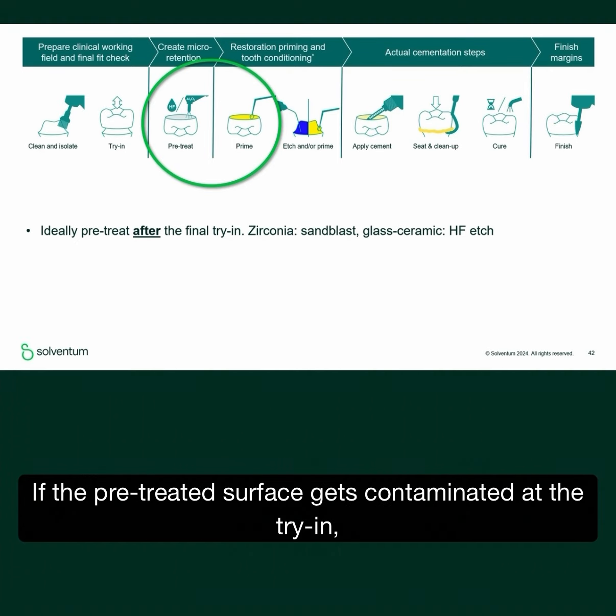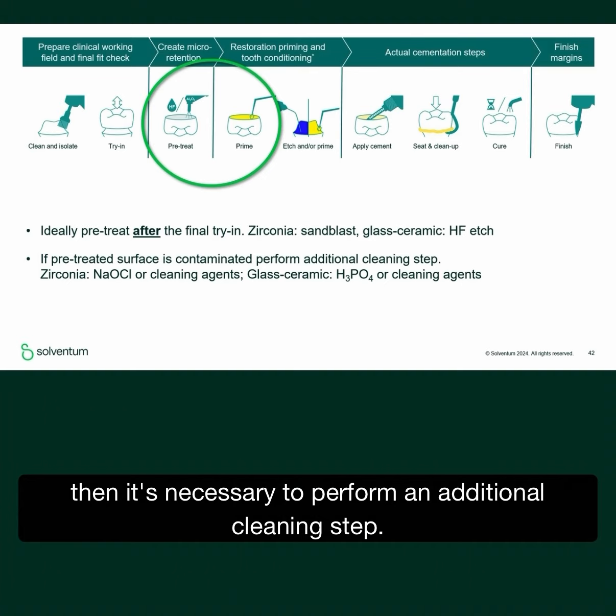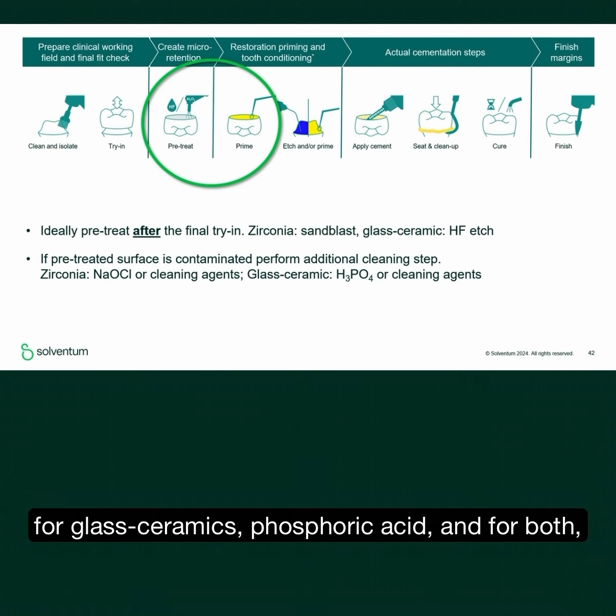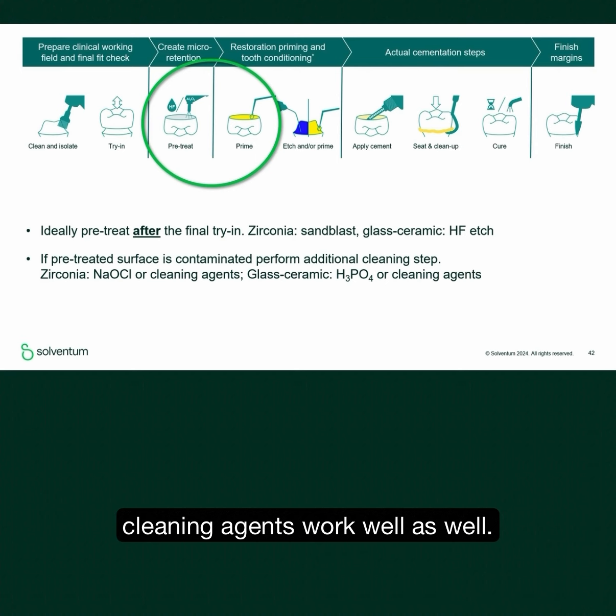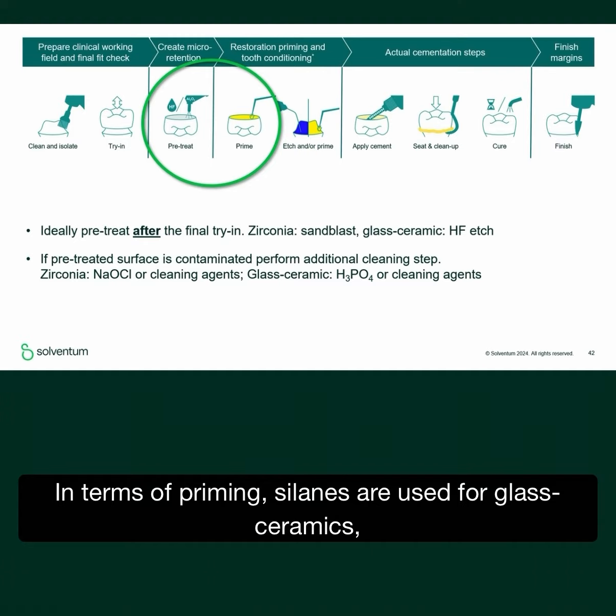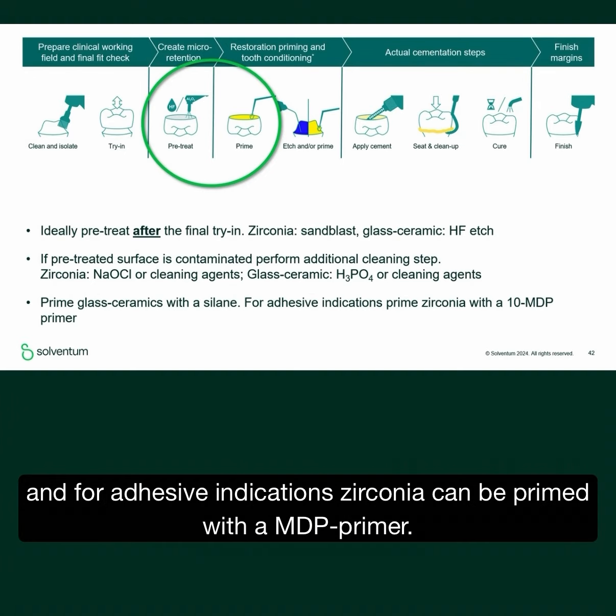If the pre-treated surface gets contaminated at the try-in, then it's necessary to perform an additional cleaning step. For zirconia, sodium hypochlorite is an option. For glass ceramics, phosphoric acid, or for both, cleaning agents work well as well. In terms of priming, silanes are used for glass ceramics, and for adhesive indications, zirconia can be primed with a 10-MDP primer.